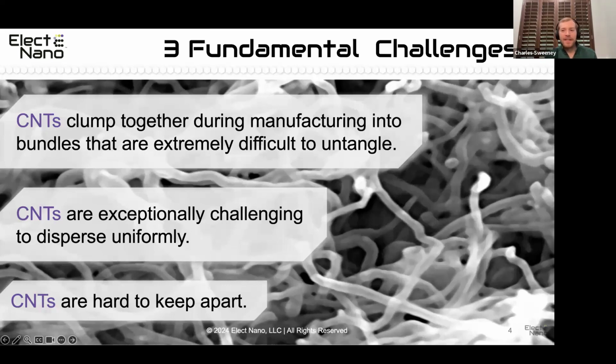But the reality is, if I really want to scale that up and use it in an industrially relevant way, nanotubes are just really challenging to untangle. The degree of intertwined, bundled, almost like a cotton ball effect that you see in what's coming out of your reactor, it's very challenging to disperse that at scale, especially in high viscosity systems, thermosets and thermoplastics that are relevant for composites.